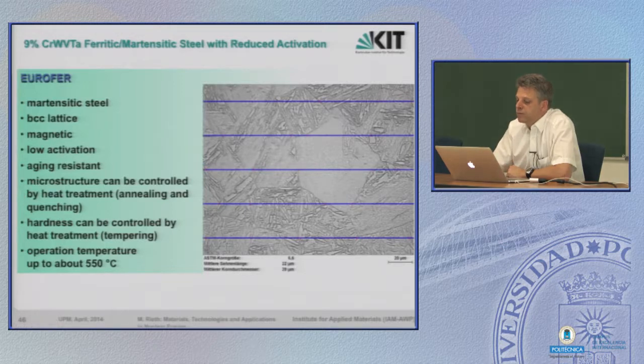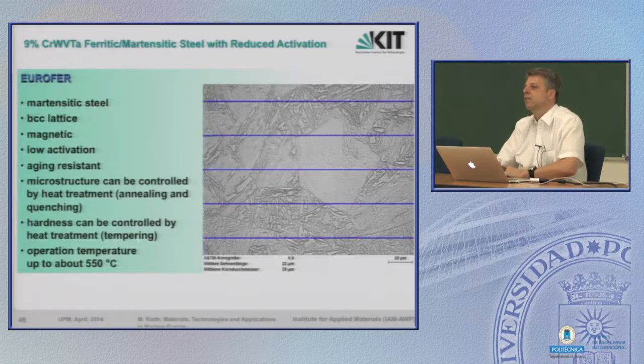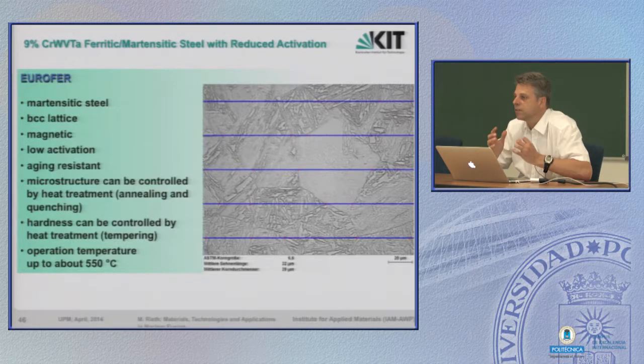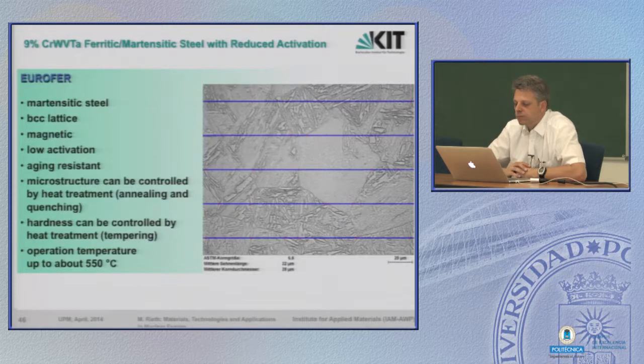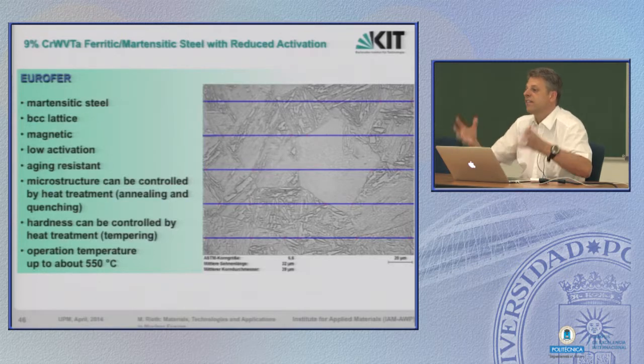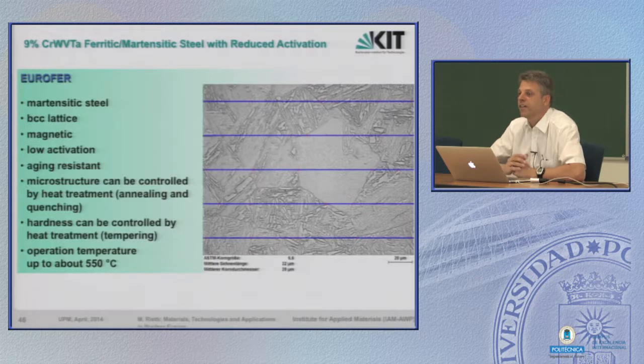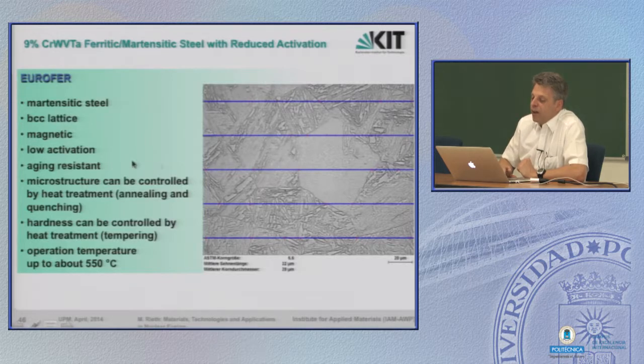That's the big difference to the austenitic steels. Let's assume you have a component, for example, such a, let's say, breeding box. And, well, after some time, somebody gets the idea the microstructure is not good enough, you want to have it finer or whatever. You can take the whole breeding box, put it in a furnace, restructure it, and, well, I will come to this point later. In any case, by mere heat treatment, you can change the whole microstructure and with that also the material properties. The operating temperature is limited to 550°C. This is also due to creep properties.